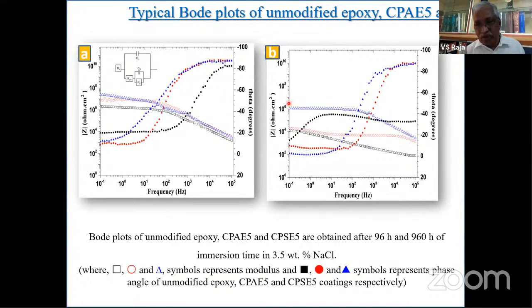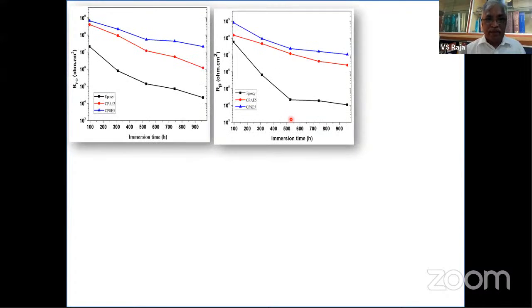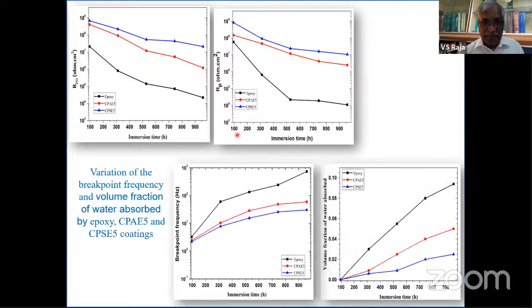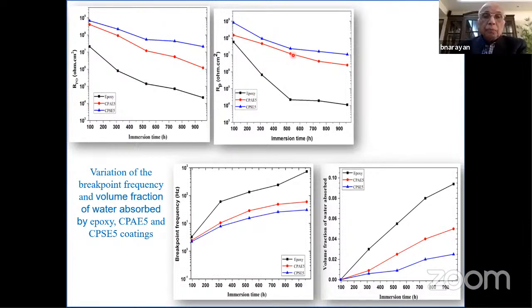It's really good, and so the performance of this is certainly very good, no problem, in terms of corrosion resistance. And again, of course, this summarizes the data that you see here. What you see in this case is the resistance of this coating versus the immersion time. You can see this 10 power 9, the decay is not going to be that sharp. And the neat epoxy, you can see that there's a sharp decay in terms of resistance here. So the modification of this molecule with these additives has given rise to a significant improvement in the corrosion performance of the epoxy.